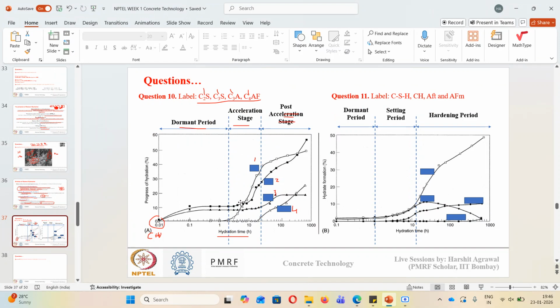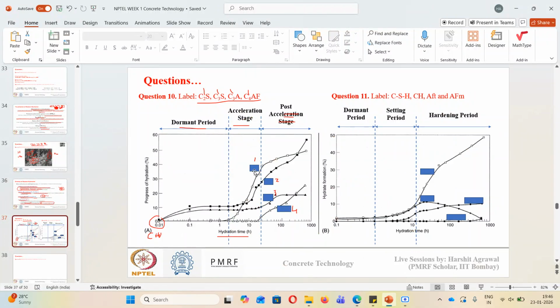So what will this first curve represent? Which phase: C3S, C2S, C3A, or C4AF? You can see the reaction of this first curve starts just after the 1 hour mark, then grows in the acceleration stage, and then slows down in the post-acceleration stage. So what can this be? Okay, so this will be C3S.